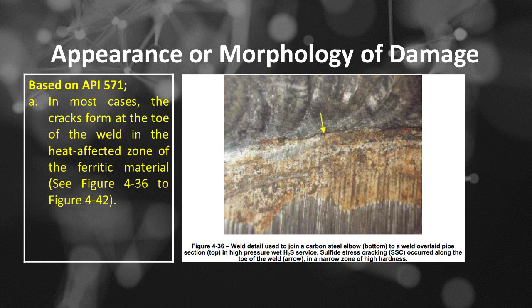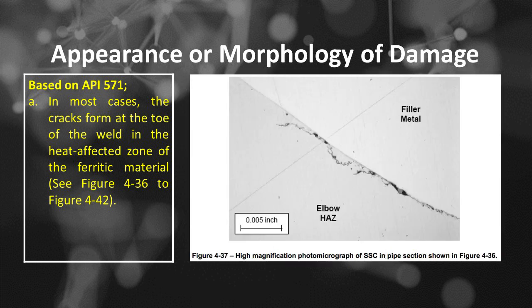Appearance or morphology of dissimilar metal welds damage mechanisms based on API 571. In most cases, the cracks form at the toe of the weld in the heat-affected zone of the ferritic material. See Figure 4:36, weld detail used to join a carbon steel elbow, bottom, to a weld-overlaid pipe section, top, in high-pressure wet H2S service. Sulfide stress cracking, SSC, occurred along the toe of the weld, arrow, in a narrow zone of high hardness. See Figure 4:37, high magnification photomicrograph of SSC in pipe section shown in Figure 4:36.